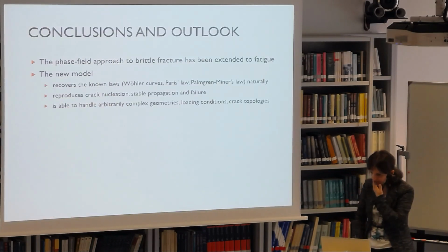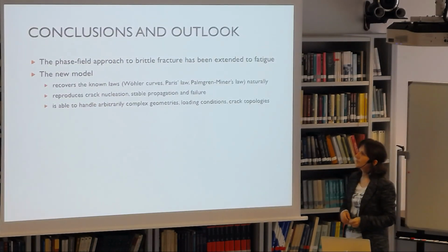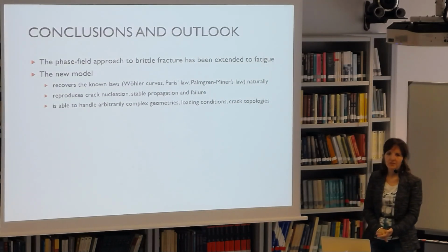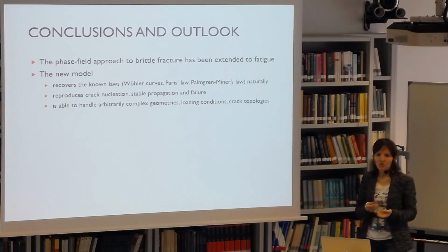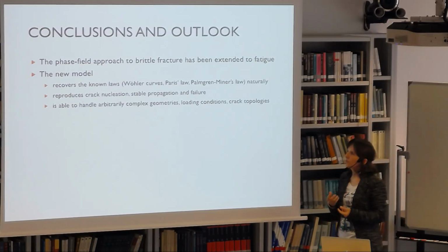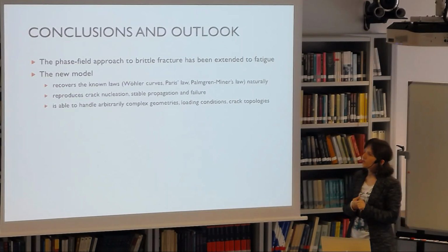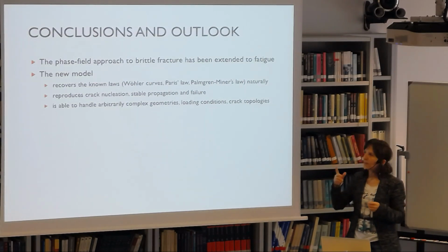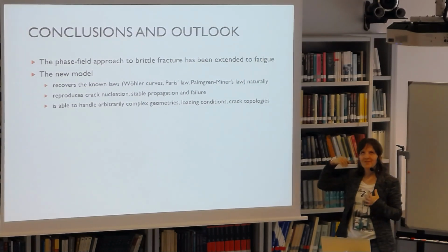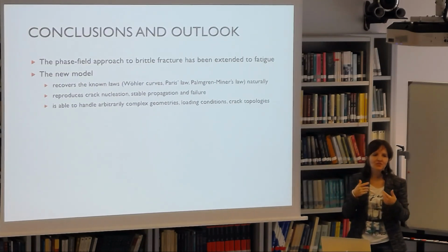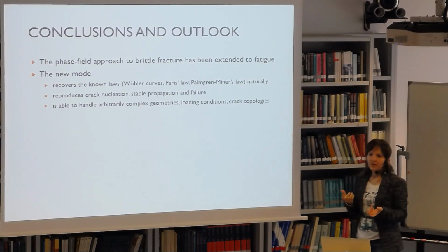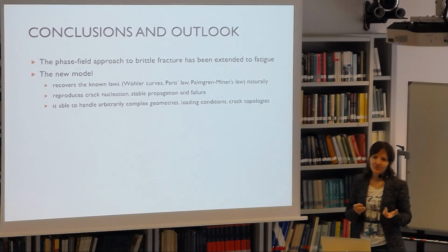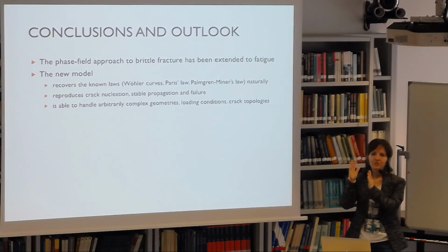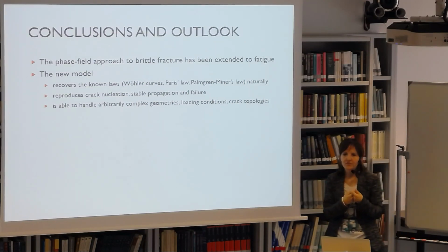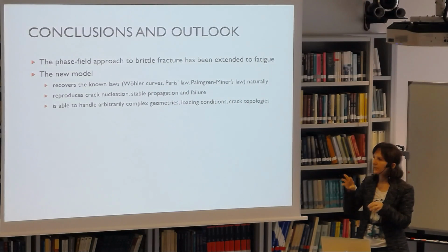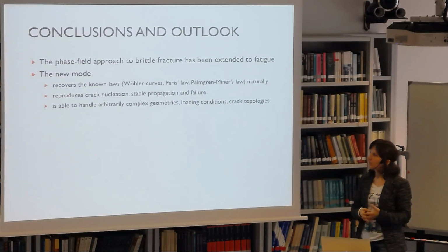So then, as conclusions, regarding especially this fatigue part, the phase field approach to brittle fracture has been extended to fatigue. The new model recovers what is known about fatigue in terms of Wohler curves, Paris law. What I didn't show you is that we also found out that the model can recover, in the simple cases where the so-called Palmgren-Miner law is applicable, the Palmgren-Miner law. Naturally, without any extra ingredient. In addition to Paris law, which only covers the stable crack propagation phase, this approach can also reproduce nucleation and also final failure, which are specimen dependent, and is able to handle arbitrarily complex geometries, loading conditions, and